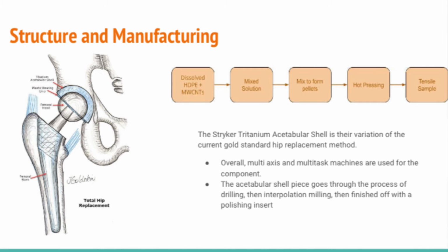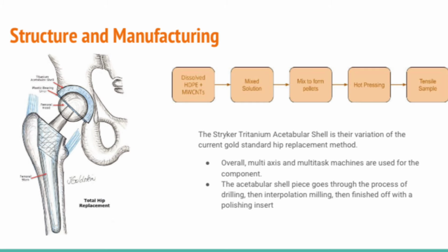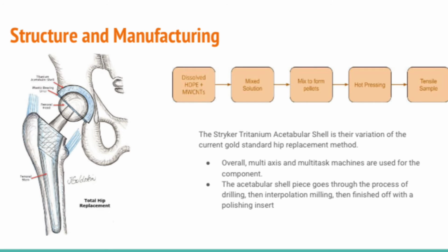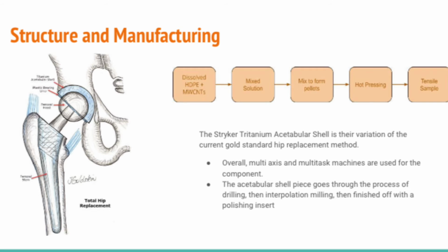This mix is then produced to form pellets, and then hot pressing occurs. Hot pressing is, of course, the process used for shaping fiber reinforced thermoplastics. The pellets are melted and then spread through the reinforcement to make the wanted shapes of the hip replacement. However, many times before the full part of the hip replacement is completed, the composite will go through tensile sample testing. Then the part is created and will go through the series of aforementioned tests.